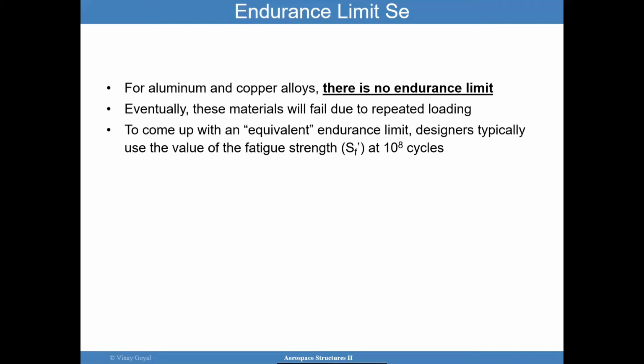For aluminum and copper alloys, there's typically no endurance limit. A lot of people think there is, but there's not. Eventually, these materials will fail due to repeated loading. To come up with an equivalent endurance limit, designers typically use the value of fatigue strength at 10 to the 8 cycles to go for a robust design.